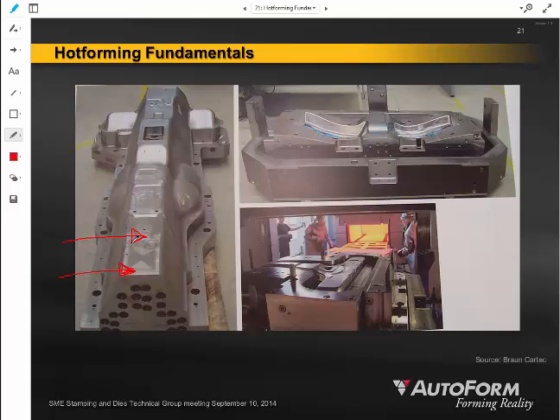As far as the other challenges, the coating, right? There's an aluminized coating. We coat those blanks that we're going to stamp in hot stamping. You can't put zinc on them. If you put zinc on them, the zinc would just melt off at 900 degrees Celsius. It would essentially vaporize. So those blanks are not zinc coated. They're not regular galvanized. We're instead using a aluminum-silicon type coating, which is highly abrasive.